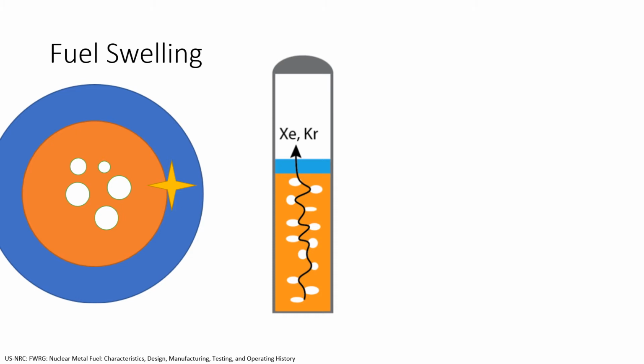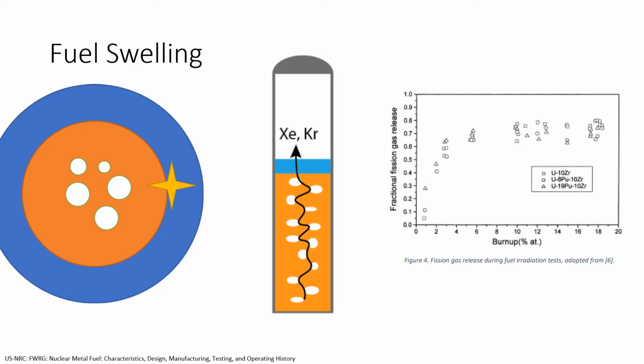The release of gas allows the material to relax and reduce swelling. An optimum smear density of 75% was found to allow swelling in the cladding without much pellet-clad mechanical interaction. The transition from closed to open pore structure is gradual due to the statistical nature of fissioning. Usually this is measured as fission gas release as a function of burnup, as shown here.